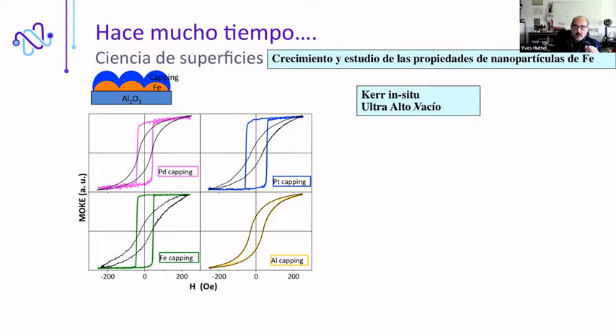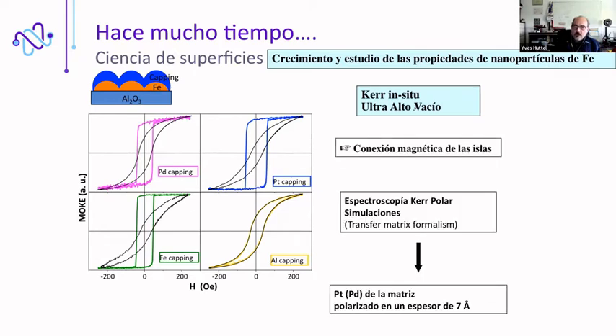And what we found is that there is a connection between the nanoparticles when we deposit, of course, iron, because we form a continuous layer of iron, but also with platinum and palladium. And this was caused by a polarization, magnetic polarization of the capping layer with a thickness of 7 angstrom approximately.